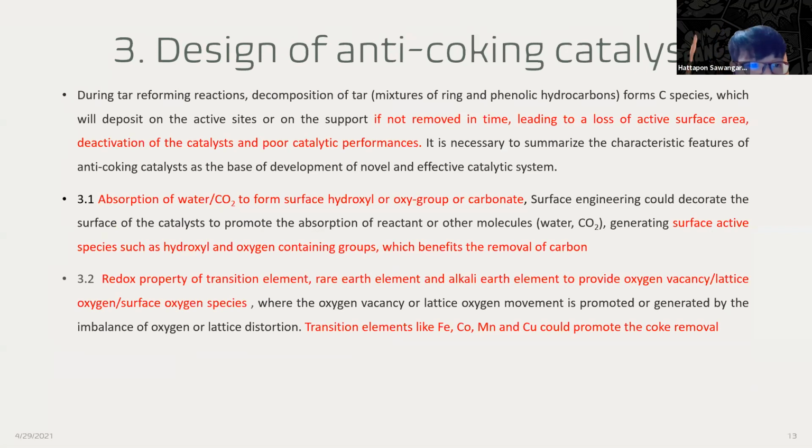First, absorption of water and carbon dioxide forms surface hydroxyl or oxy groups, carbonates. Surface active species such as hydroxyl and oxygen-containing groups benefit the removal of carbon.